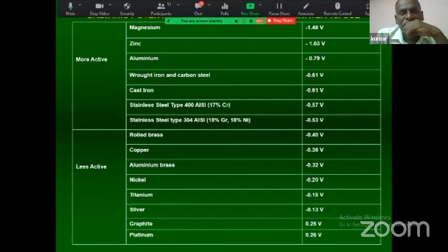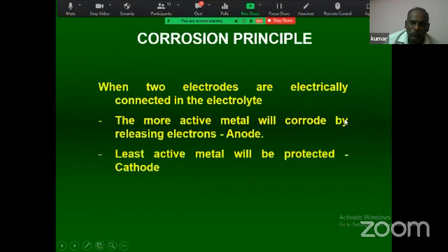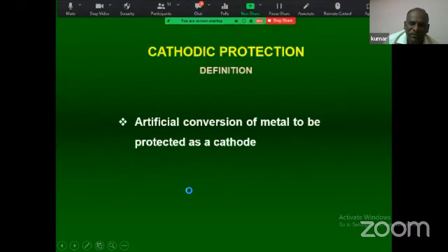When you want to have protection for the steel, if you want to give a sacrificial system, then you can connect like this. Any material you want to protect has to be connected with a more active material, then the material will be protected. That is the principle of cathodic protection. I am coming to the principle. The more active metal will corrode by releasing electrons, that is the anode. The least active material will be protected, which is the cathode. So this is the general corrosion principle. In cathodic protection, artificially you are converting the material to be protected into a cathode.